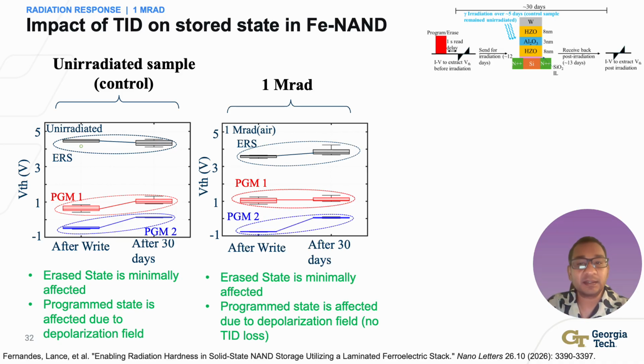The 1 megarad in air result closely tracks the control. The erased state remains stable. The programmed state movement after 30 days is comparable to the unirradiated relaxation. We therefore observe no clear additional TID loss in the stored states at 1 megarad.